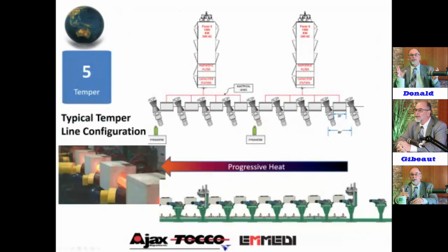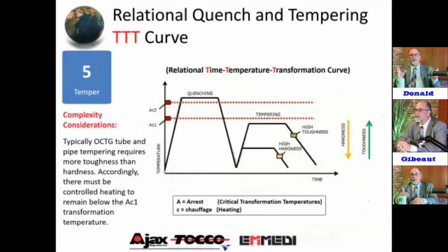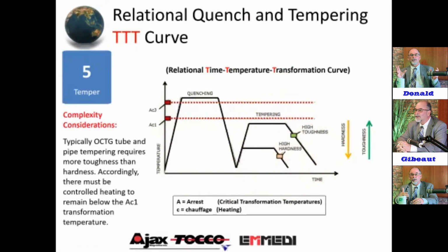The temper line is basically the same as the austenitized line. Here you can see we have lower frequencies in this particular one, 300 hertz and 500 hertz, which goes back to that reference depth of current penetration we talked about, because the temper is all below the magnetic Curie point heating, so we're shallower in that depth of penetration. And here's actually the curve showing the AC3 and the AC1 lines for the quench. In relation to temperature and time, we can adjust the hardness and we can adjust the toughness and ductility in the temper by time at temperature.